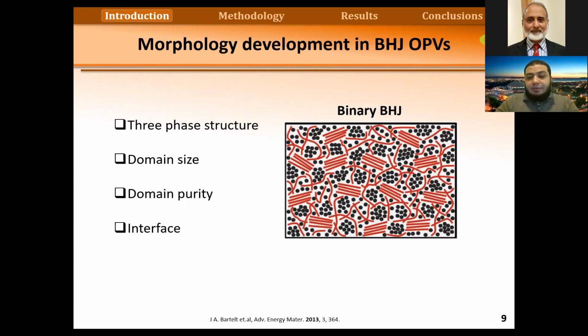For example, if we have very large domains, then we have low interfacial area, and the interfacial area is the place where the charges are generated. So we might have low efficiency. Also, if we have very small domains, the charges will not be able to reach the electrodes. They can be trapped in the smaller domains. So we need a specific domain size, and also a specific domain purity. If we have impurities inside a domain, we are creating traps, and these traps will also affect the efficiency.